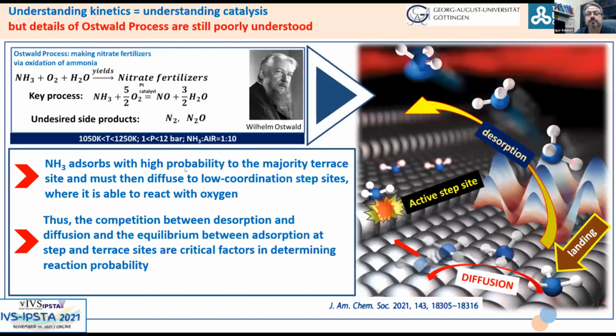Now, let's look at some of the microscopic steps which are happening during this reaction. The ammonia molecule lands on the majority terrace sites. Then, in order to react with oxygen, it must diffuse to the low coordinated active step site where it reacts with oxygen atoms.